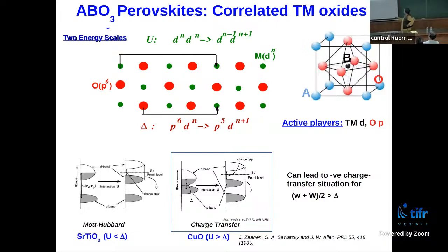A different picture shows up if you are the late transition metal. See, in this case, the transition metal was titanium. In this case, it's a late transition metal, copper. And in this case, by turning on the interaction, because U is much larger than the delta, the gap opening happens between the filled oxygen p bands and the empty upper Hubbard band. And the gap is a charge gap rather than a Mott gap.